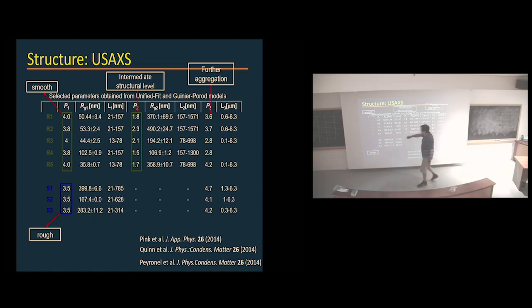The roll-in shortening is here, and these are commercial ones, 20 kilogram boxes from the store, made by the big machines. And these ones here, they didn't know we were doing that with their samples. We just get samples from everybody and then analyze them and see where they are, but we didn't disclose where we got them from. But notice immediately that for the roll-in shortenings, you actually have 3 structural levels. There's 1, there's 2, and there's 3. And for the all-purpose shortening, which was brittle, we only have 2.